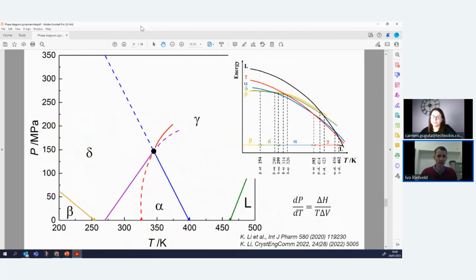And with that, we get to the end of the presentation, this is basically the conclusion. So on the left-hand side, you have a pressure-temperature phase diagram of all these 4 phases of pyrazinamide, in which we have clearly in the center alpha as a stable form at room temperature and under, say, 0 pressure. 1 bar is not very much. If you can see, we go up to 150, 200, 250 megapascal. So 1 bar, that is 0.1 megapascal. So we're really at the lowest line there where we live, so to say.